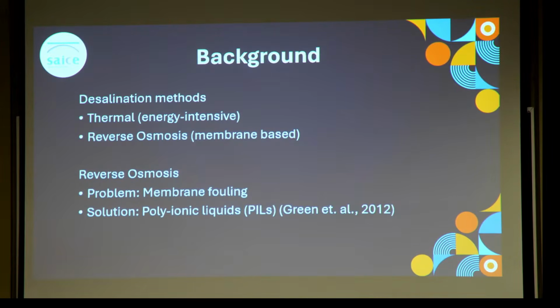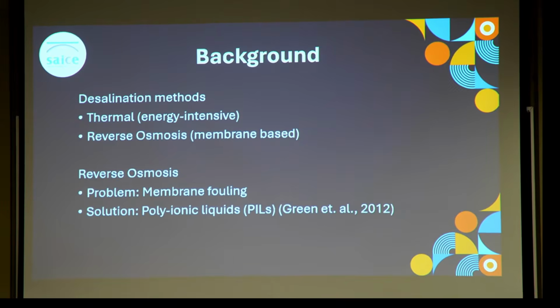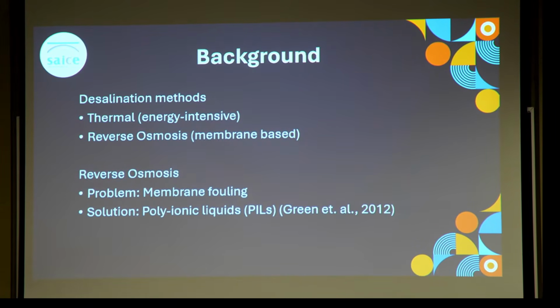Due to this, researchers have conducted many studies involving the effect of polyionic liquids on membranes, and this research has shown us that excessive amounts of polyionic liquids can actually be detrimental to membrane performance, as it compromises the selectivity of the membranes. However, all of this research focuses on remaining safely below that upper limit. In contrast, our study deliberately approached this threshold, aiming to identify the precise point at which performance begins to decline, which is a boundary that has not yet clearly been defined.